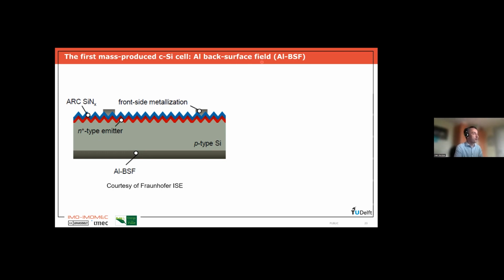So this is what you could call the first mass-produced crystalline silicon cell. It started being produced 15 years ago or so. And the cell structure is shown here. You typically have a P-type silicon wafer as a starting point, which can be multi or monocrystalline. Then at the front, you have an N-type emitter. So you have a P-N junction that you need to separate the electrons and the holes. The front surface is typically textured with random pyramids so that you have a lower reflection and a better light coupling. And then you have at the front a silicon nitride layer that acts as an anti-reflection coating and also as a passivation layer for the front surface.